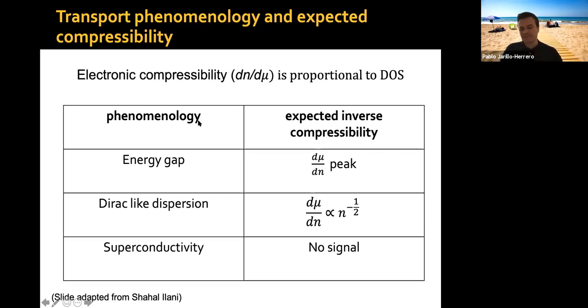Therefore, the phenomenology is the following. If you have an energy gap, since you have very little density of states, you should have a zero compressibility, or a peak, a maximum, in the inverse compressibility. If you have a Dirac-like dispersion, it's also a low density of states, so you should have a minimum in compressibility or a maximum in the inverse compressibility, and in particular, a maximum that is proportional to one over the square root of the density. So a maximum that decreases in a particular way. If you have superconductivity, you actually don't measure anything with a thermodynamic probe, at least to zeroth order. Superconductivity is a gap that appears always at the Fermi energy. It's not a gap which is there in a thermodynamic sense.